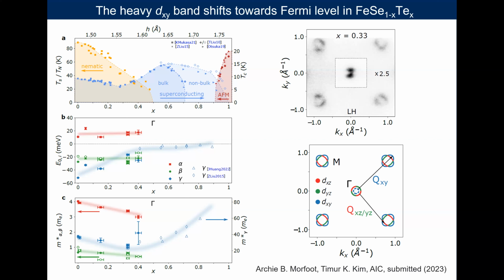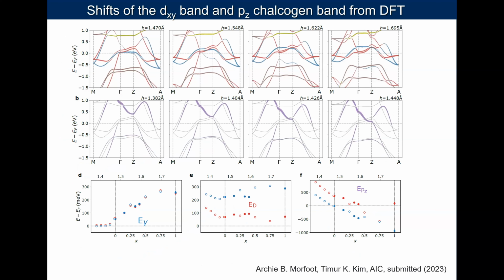It's worth mentioning these materials at the 50-50% concentrations are the materials proposed to host topological superconductivity. If we are looking at the DFT as a guide, which usually provides guidance about the trends of the system, but does not provide the exact value because the Fermi surfaces are shrinking. So when we calculate the changes of the dxy band, this is the blue band here, by changing the chalcogenide height, as you add tellurium, you move the tellurium away from the conducting plane. And the calculation predicts that this band should move up. And here we plot how this shift occurs.